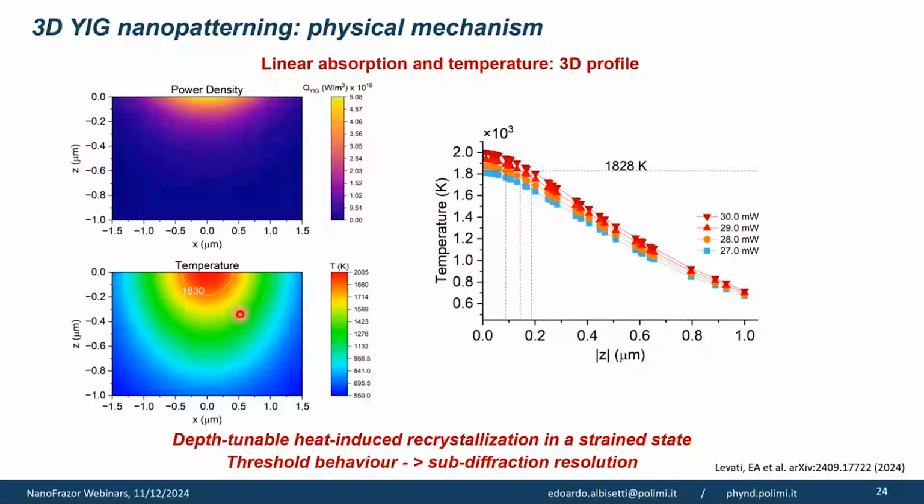So it's a melting that happens at that precise temperature, more or less. And so what is going on is that if we have a Gaussian beam and we tune the beam so that only the peak actually overcomes the transition, then we can achieve subdiffraction resolution in the final pattern, because we are convolving the Gaussian beam with a really peaked transition.